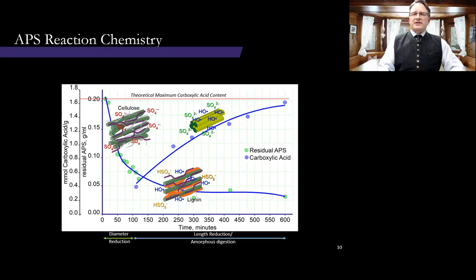So ammonium persulfate chemistry is pretty interesting. It's activated by heat, and once activated, it very rapidly dissociates into its reactive ions, the first being the sulfate free radical. And so if you look at this diagram, the first reactions that start to occur are hydrolysis reactions that reduce the diameter of the fibers, and at the same time convert the surface hydroxyls to an aldehyde form.